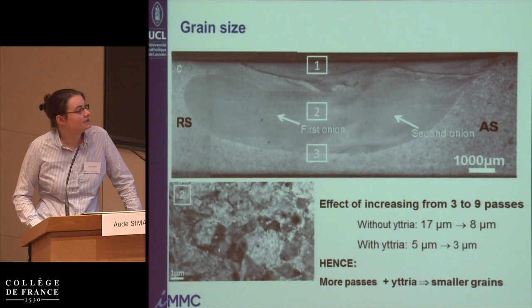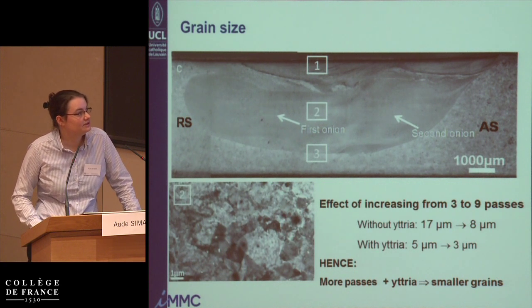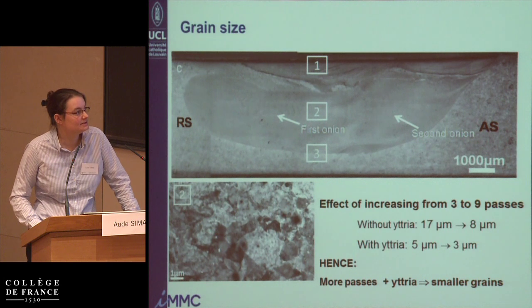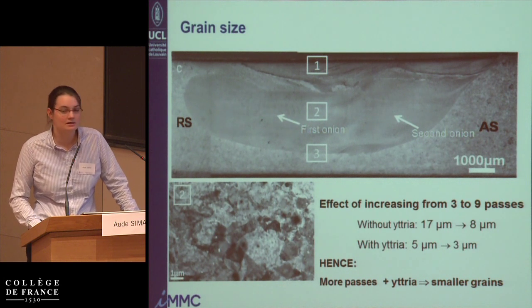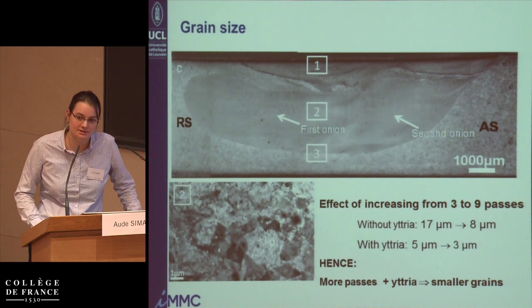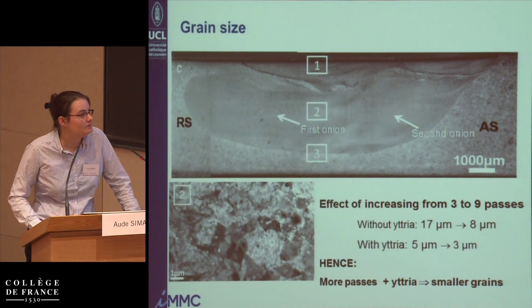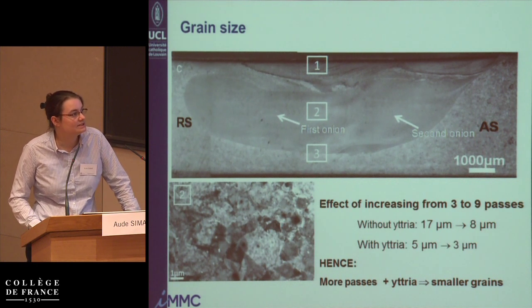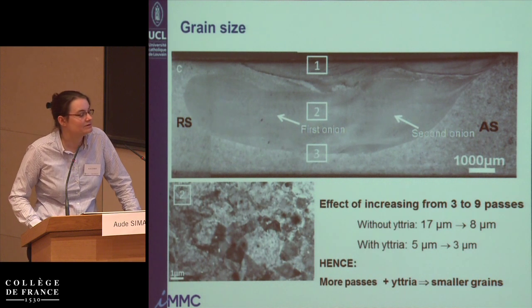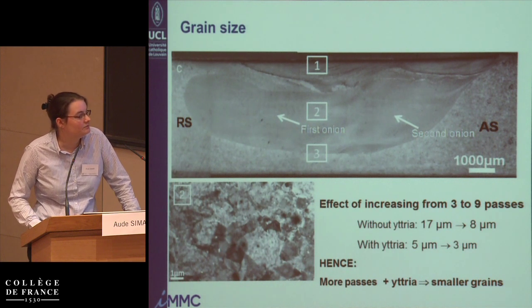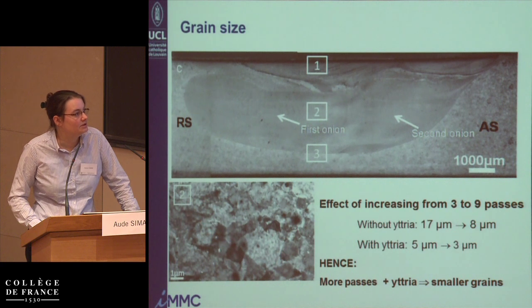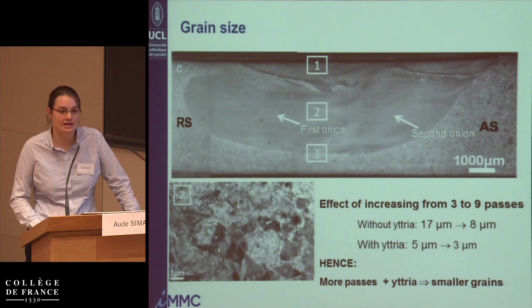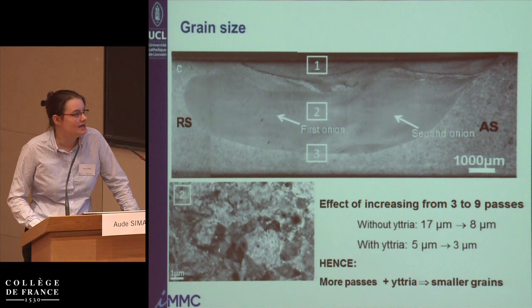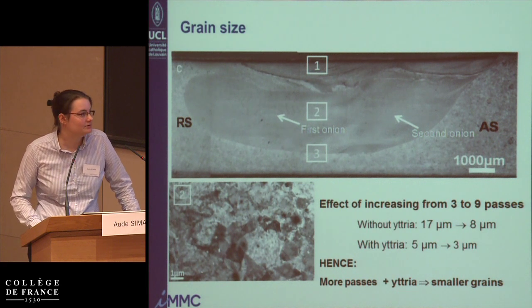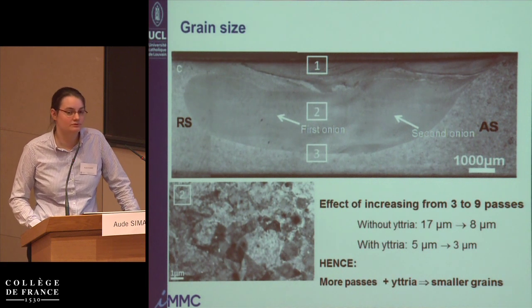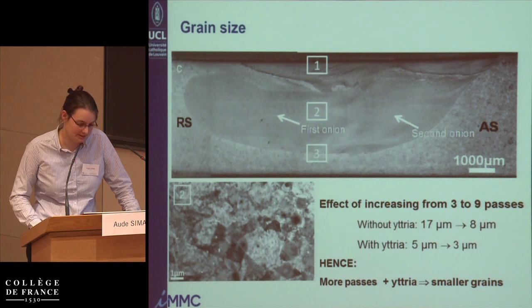So looking at the grain size, the effect of increasing from 3 to 9 passes, without yttria, I told you that friction stir processing decreases the grain size. Well, without the yttria particles, you already have a decrease of the grain size, and you can reach 8 microns in grain size. And with the yttria particles, you can even reach smaller grain sizes, 3 microns typically.